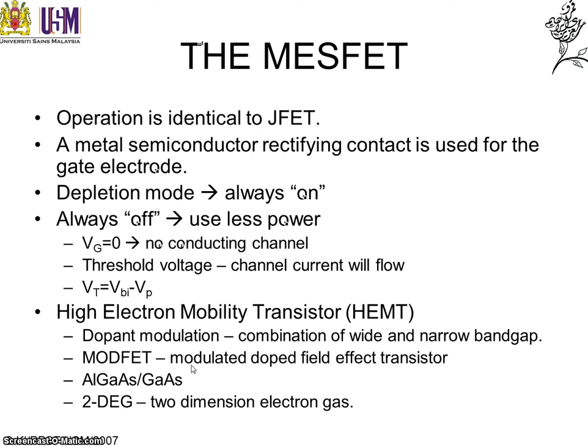The reason you can create HEMT is because you can do some bandgap engineering with the 3-5 compounds. In order to maintain high transconductance in the MESFET, the channel conductivity must be as high as possible. One way is to increase the doping, although if you increase it too much, it causes increased scattering by ionized impurities, which brings the mobility down. So a way of creating a high electron concentration in the channel, by means other than doping, is to grow a thin undoped well — which is gallium arsenide — bounded by a wider-gap material.